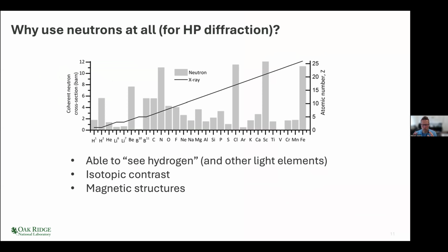So why might neutrons be interesting? Why might you be interested in doing neutron diffraction? Well, the most common thing which is said about them is that neutrons are able to see hydrogen. And this graphic shows the gray bars are the scattering strength of the various atoms and isotopes. And the solid line is showing the scattering strength seen by X-rays, which is, of course, proportional to atomic number. So there are these advantages.